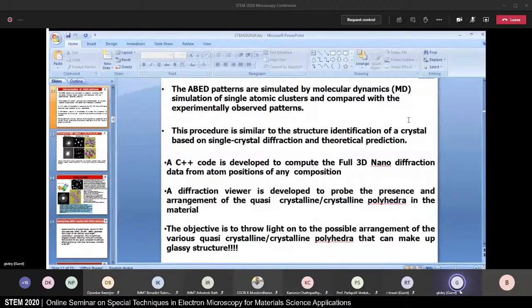of the cluster. So we use a C++ code to develop a full 3D nano diffraction data from atom positions for any composition. A diffraction viewer is developed to probe the presence and arrangement of the quasi-crystalline polyhedra in the material. The object is to throw light onto the possible arrangements of various quasi-crystalline polyhedra that can make the glassy structure. So that is all about the background.